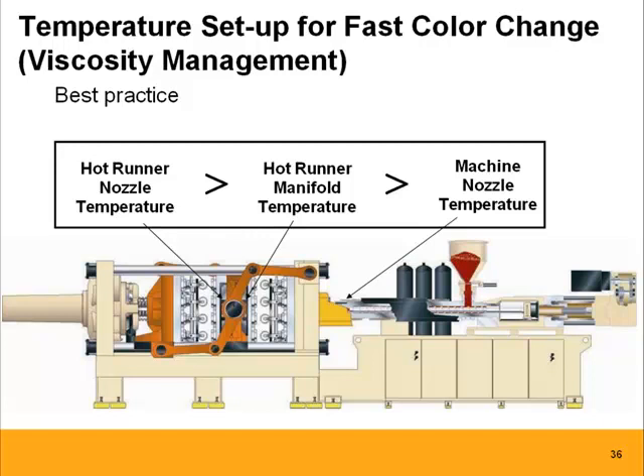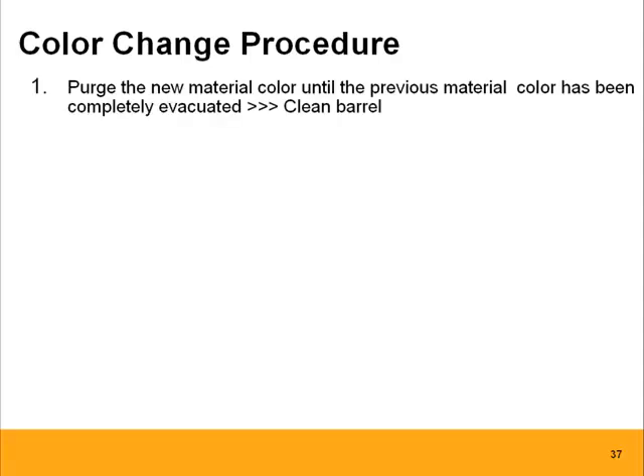So how do you actually do a color change procedure? The first thing is always to purge the new material from the screw and barrel. We always recommend that. Sometimes when you go from light to dark, you can just change in the hopper. But typically, we would recommend to first clean the barrel, and it usually goes pretty fast, and start fresh there. Then we clean the machine, and cleaning is looking at, for example, the interface of the sprue bushing. Sometimes a little bit of resin leaks out, or the nozzle wasn't seated properly. So clean the machine nozzle and the hot sprue. This is, by the way, also a good time to double check if the orifices match.